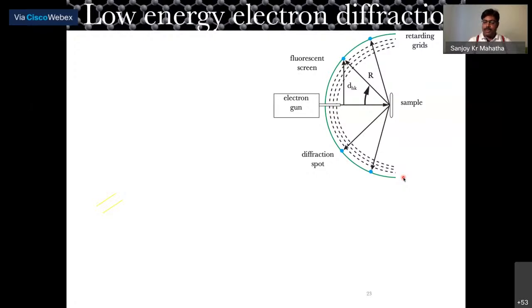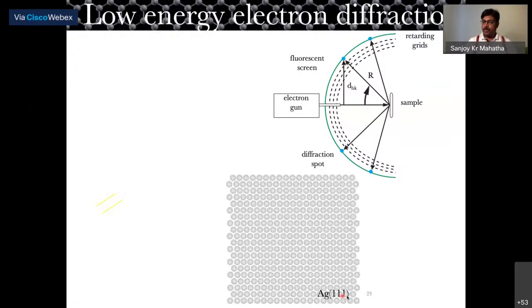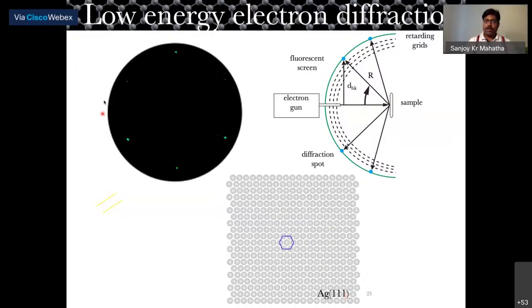For example, let's say we start with silver 111, on which we have grown silicene, it has a hexagonal symmetry. And if we shine this material with the electron beam, we will see a diffraction pattern on the fluorescent screen like this. So it will have 6 spots, basically with a hexagonal symmetry. And from this, we can construct the Brillouin zone, right, which will also be hexagonal. And then we can also know what the symmetry directions are. Like this is gamma to M, this is gamma to K.